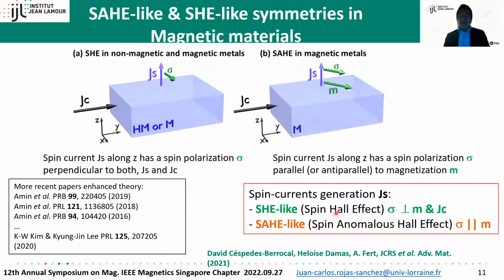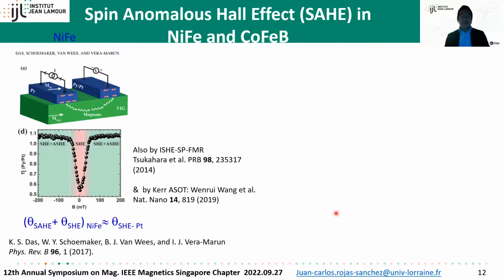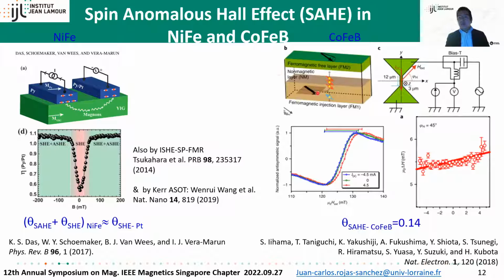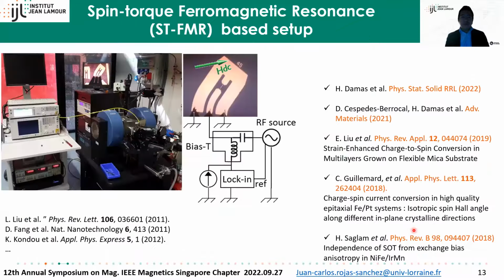Actually, the spin anomalous Hall effect and spin Hall effect in magnetic materials have been measured experimentally. For example, in this work by Vera-Marun, where they report the overall efficiency for permalloy similar to the one in platinum using nonlocal signals. Cobalt iron boron has also been reported by S. Iihama and co-workers in Japan, and here they report a large value of 0.14. Indeed, this is a technique that we will use, based on spin torque ferromagnetic resonance.